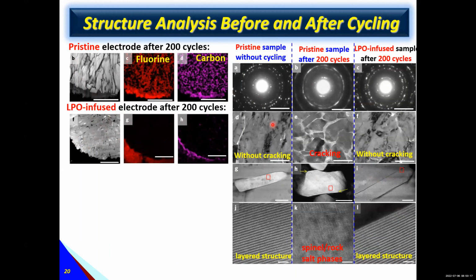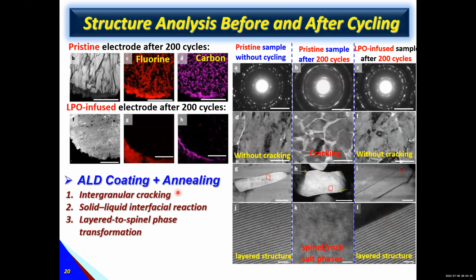Also from a higher resolution TEM, you can see, without cycling, it maintains very good structure. After 200 cycles without coating, you see that there is phase change. If we have coating and annealing, you see it maintains very good structure. So this example indicates a coating with a simple annealing can address three challenges at the same time. One is to prevent cracks, also prevent electrolyte penetration, and also prevent phase transition at the same time.